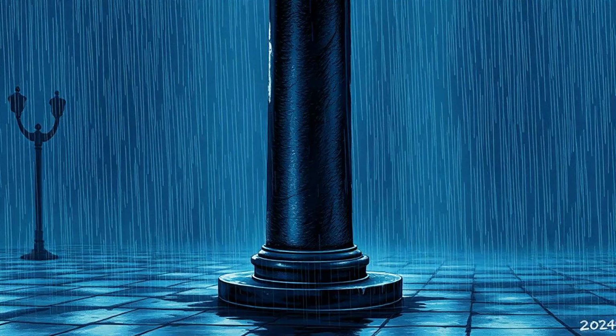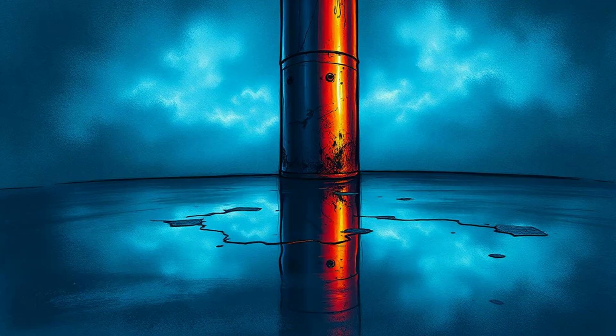Because for 1,600 years, through monsoon rains and scorching heat, this massive piece of iron has barely rusted. Normally, iron rusts very quickly when exposed to air and moisture. A modern piece of untreated iron would be a pile of orange dust in a fraction of that time. The iron pillar of Delhi, however, stands almost completely corrosion-free.